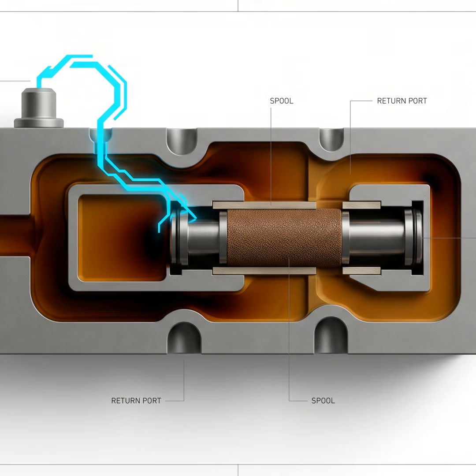We started by identifying the hidden architectural flaw driving the crisis. OEMs deliberately shrinking hydraulic reservoirs by up to 40% to advertise a smaller physical footprint and faster cycle times, creating a massive thermodynamic bottleneck that fundamentally changed the operating reality of the fluid. We explored the kinetic energy and chemistry of how that intense, relentless heat creates sub-micron varnish. We saw the temperature paradox, how the varnish remains dissolved and invisible when hot, but precipitates as a destructive, sticky resin the moment it hits the cooler servo valves.